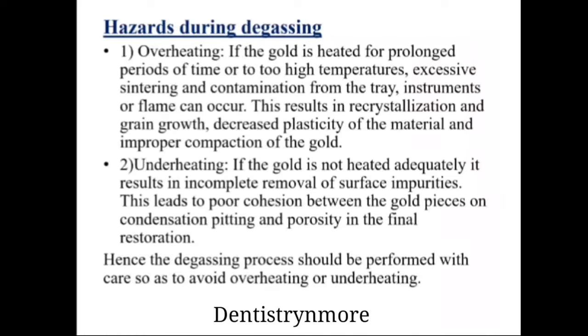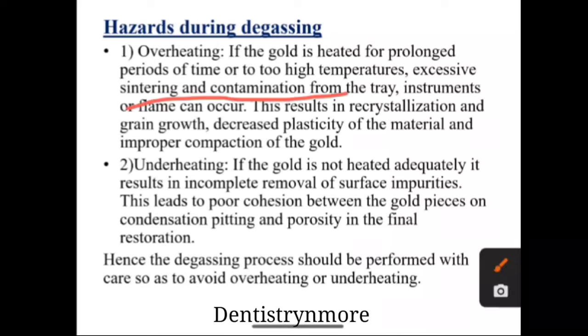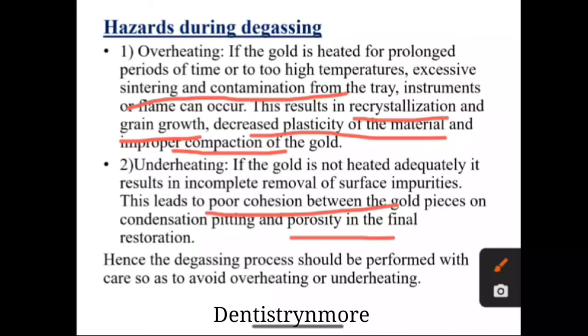Now these are the hazards during degassing. It can be overheated or underheated. In cases of overheating, that may lead to sintering or contamination from the tray. That may lead to recrystallization and grain growth, decreased plasticity of the material, and improper compaction of the gold. Underheating, if it is not heated adequately, that may lead to poor cohesion between the gold pieces, and also porosity in the final restoration can also occur.